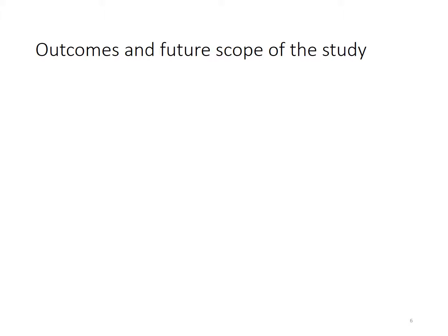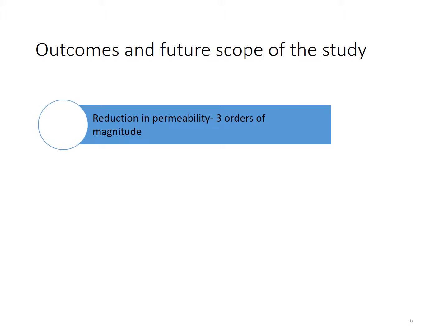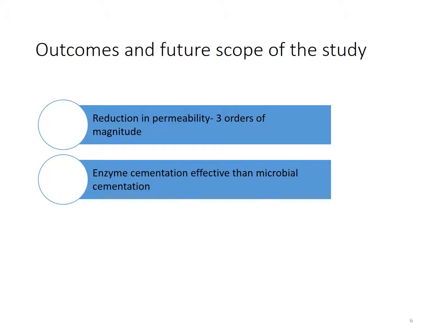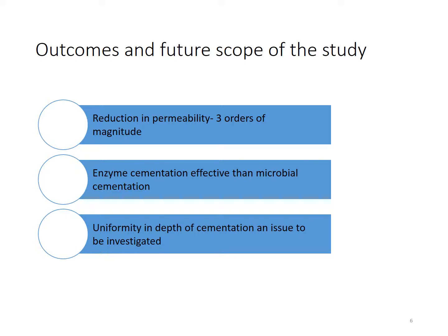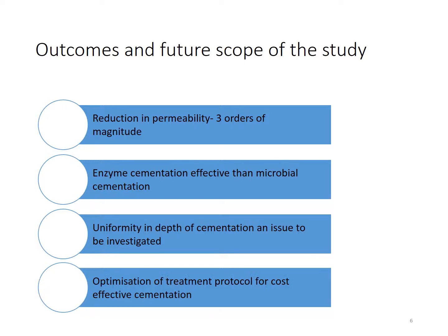From this study, it was observed that the hydraulic conductivity reduced by 3 orders of magnitude. The enzyme treatment was found to be effective as compared to microbial treatment. The depth of penetration of calcite deposition has always been an issue with respect to the uniformity in deposition. This needs to be further investigated.